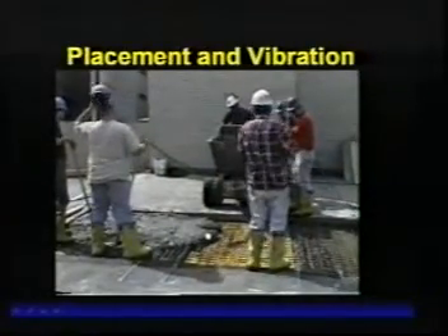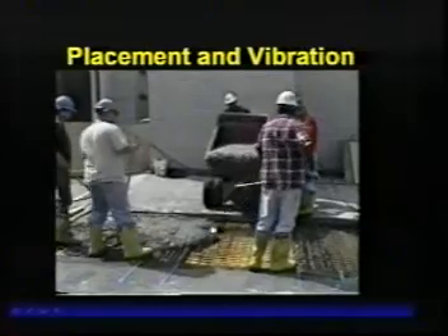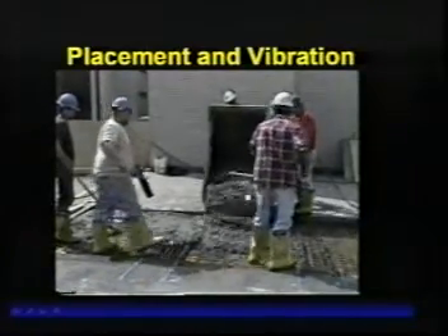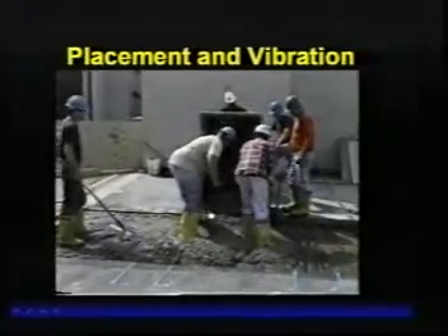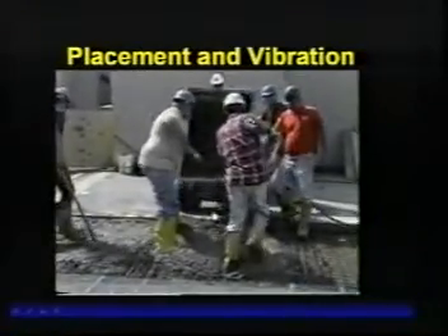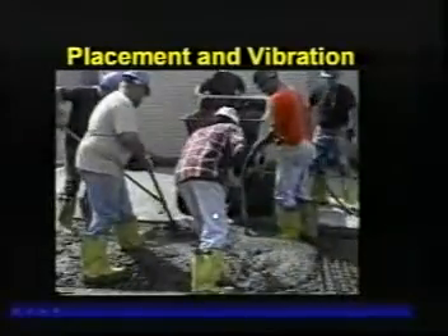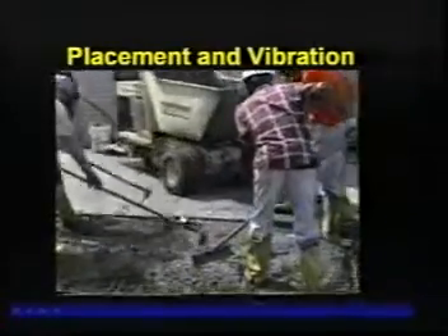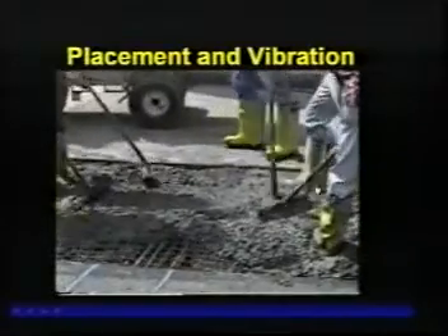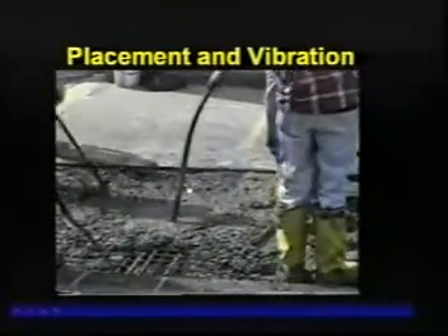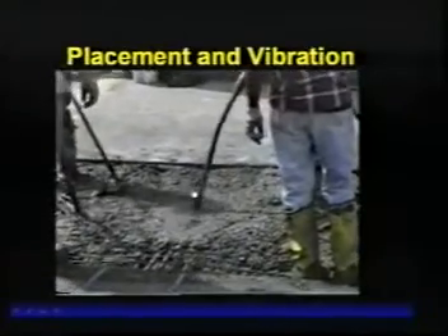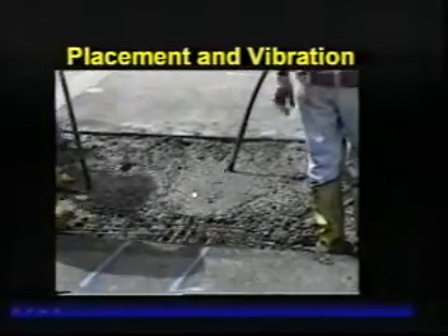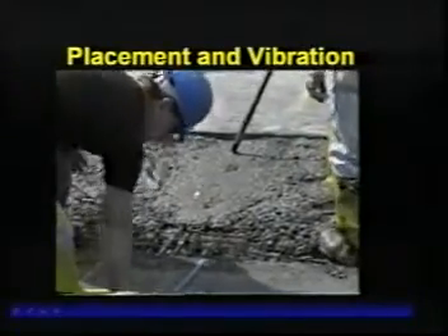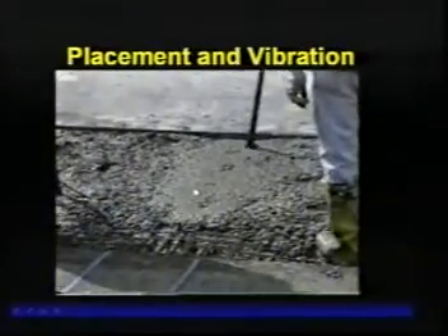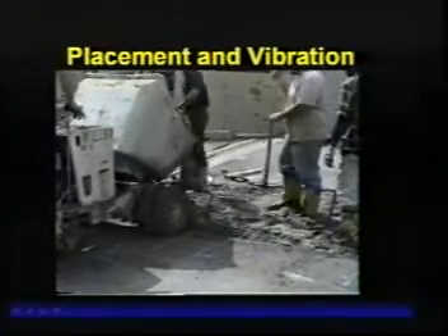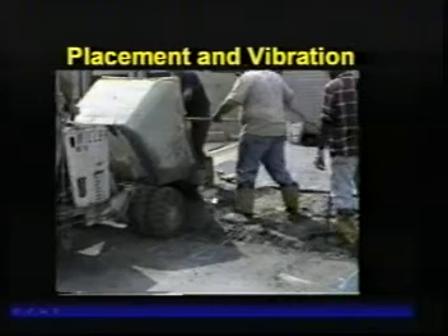This next sequence I'm going to show you is basically standard process, whether it's partial depth or full depth. And in this particular case, we're using ready mix concrete. Obviously, the placement into the location is the first step after all the preparation is done. You can see the next step after placement is the insertion of vibrators. And this is probably the step that's left out the most in these particular jobs, the lack of vibration. And it's extremely important to vibrate as in any job, even if it's 3 or 4 inches thick, to consolidate around the reinforcing steel and also to create intimate contact with the substrate.